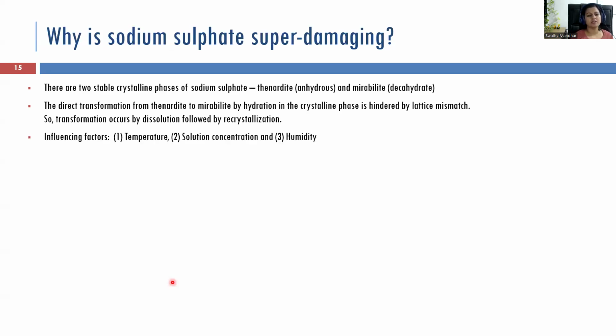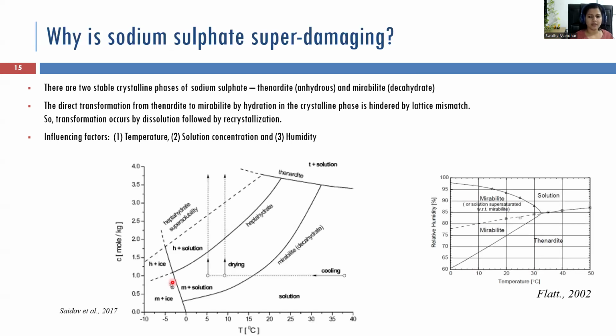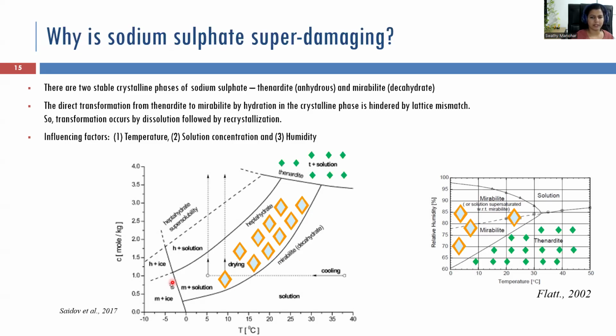The factors influencing are temperature, concentration of the solution, and humidity. These are the phase diagrams of sodium sulfate, where you can see that mirabilite, which is sodium sulfate decahydrate, will form only in some particular temperature and humidity, which you can easily assess from these graphs which are available everywhere. And these are the thenardite. The green colors denote the thenardite, which also happens at larger temperatures and higher concentration.